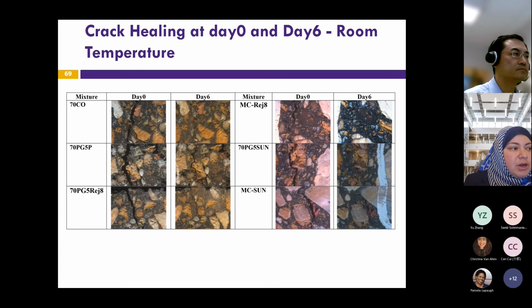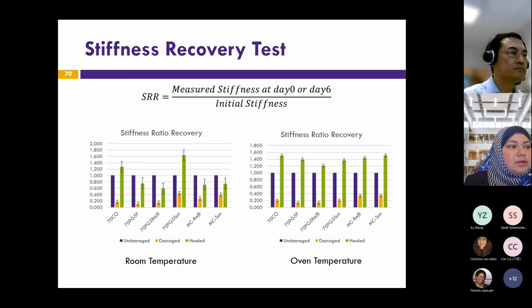This is just a sample of the results. All the mixes, the crack, and then at day 6, they are almost 100% healed. This is the stiffness recovery results, and as you can see here, this specimen, which is the sunflower oil specimen, exhibited the highest stiffness recovery.